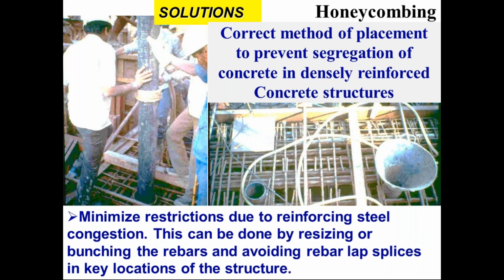You have to do full knitting together of the batches and layers of concrete under, such that when you are vibrating the top layer of concrete with a needle vibrator, it should be able to conveniently go down into the lower layer, which has still not achieved the initial or final set, and thereby monolithically get kneaded together. And this avoids the weakness in concrete and solves the durability problem. You can see here, even well compacted concrete, if the lower layer is set and the subsequent layer is put later on, can show indications of cold joints. This is one of the most important points I would like to stress.